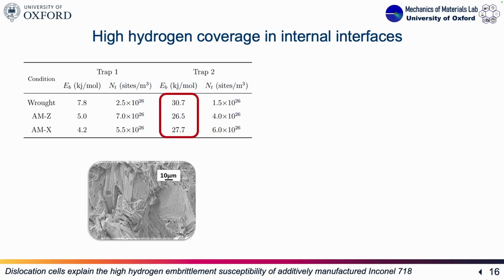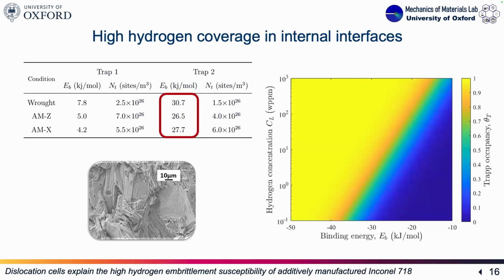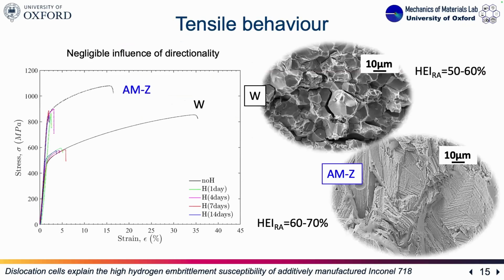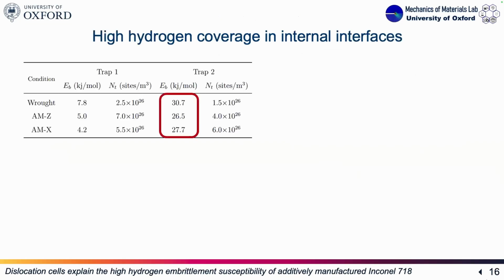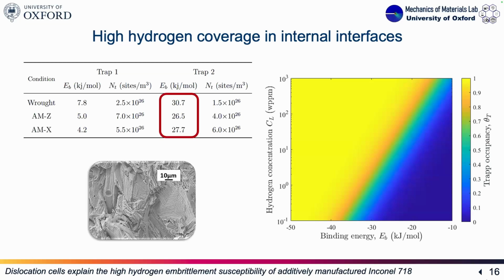And we can explain the decohesion of all the internal interfaces, both in the wrought and in the additive, regardless of the charging time, because something interesting here is that regardless of the charging time, we have a lot of embrittlement. So basically what we can see is that we have a very high trap occupancy in all these interfaces, even for small charging times. So we are more or less in this region where we have a trap occupancy close to 1.